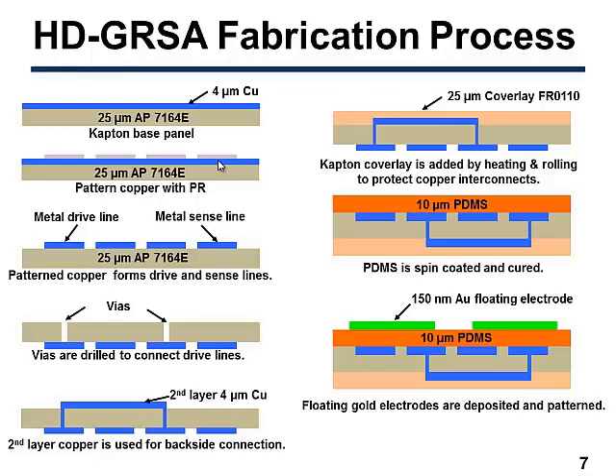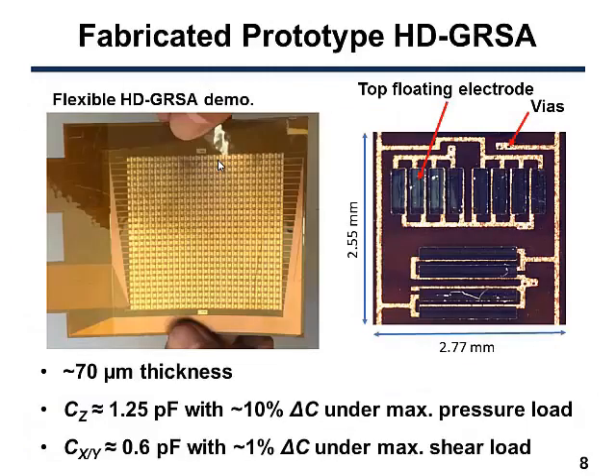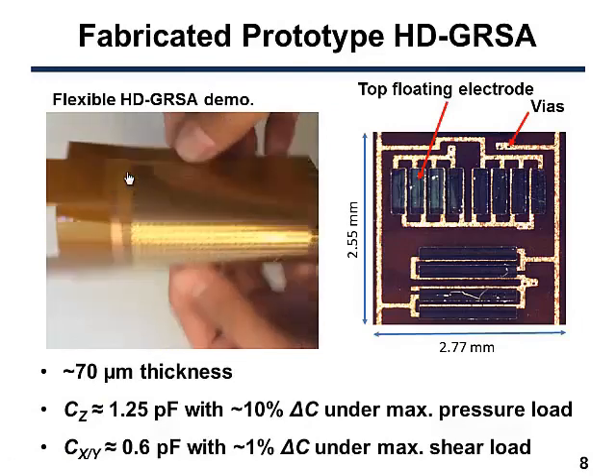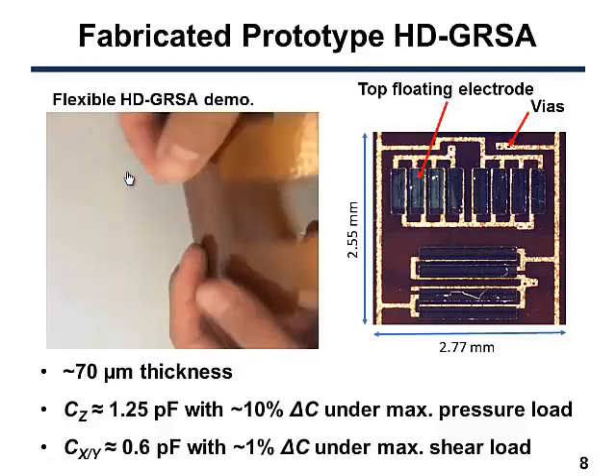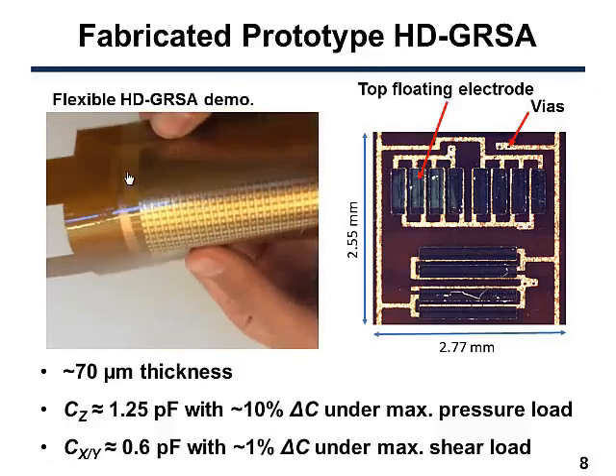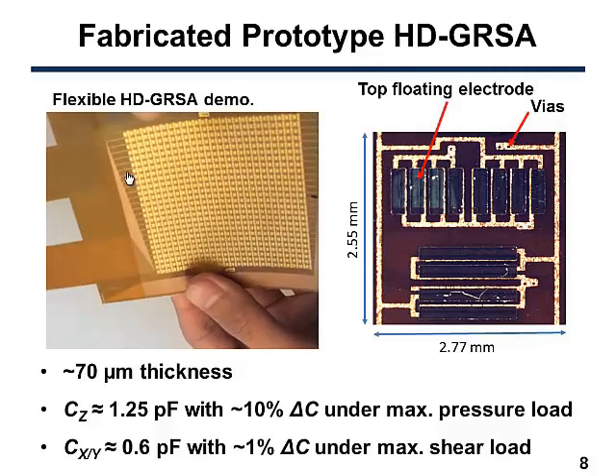Until this step, we worked with an external foundry using flexible PCB technique to fabricate our ground reaction sensor array. After that, 10 micron PDMS is spin coated in the clean room. And 150 nanometer gold is then deposited and patterned to form the floating electrode. This video shows a demonstration of our fabricated ground reaction sensor array. As you can see, it is very flexible, and it has a thickness of about 70 micron.